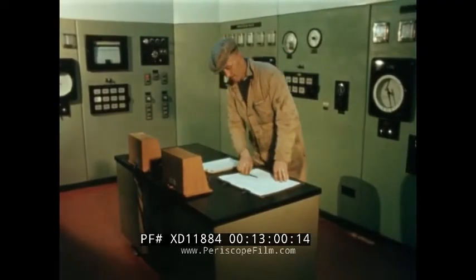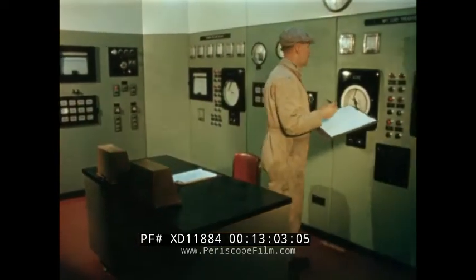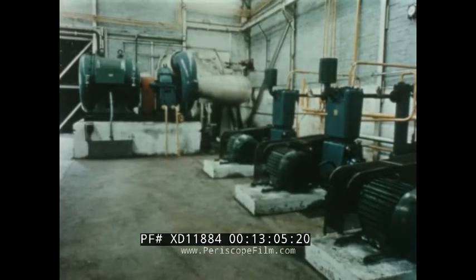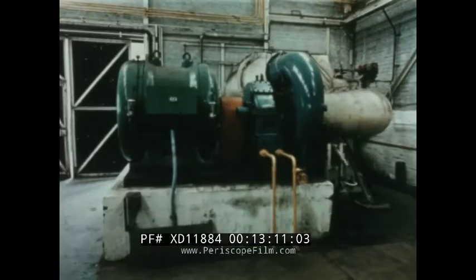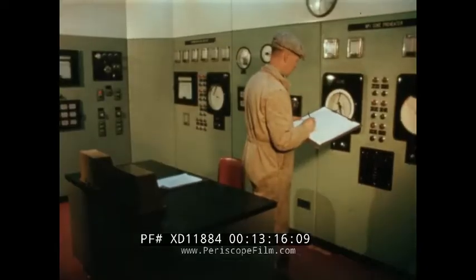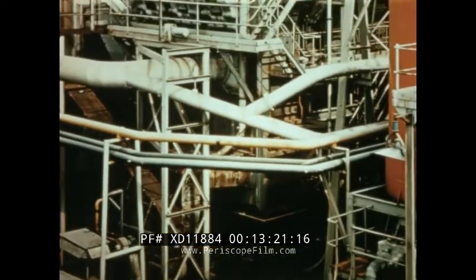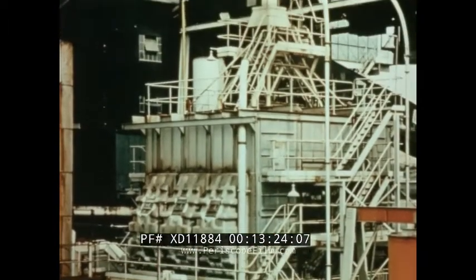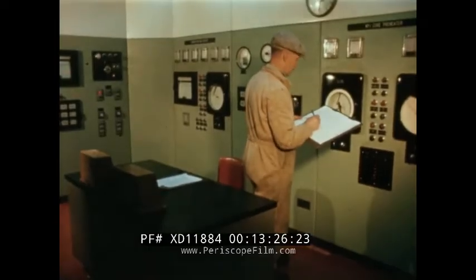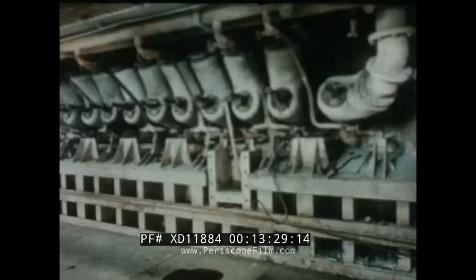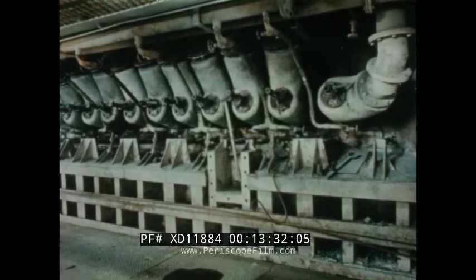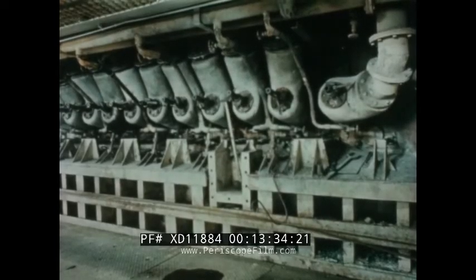This is the control room for all operations relating to smelting and condensation. The 550 horsepower blower compresses the blast air. The blast air is then brought up to 750 degrees centigrade in the air heater, which is fired by blast furnace gas. The blast air enters the furnace through these tuyeres, which also permit a glimpse into the combustion zone.